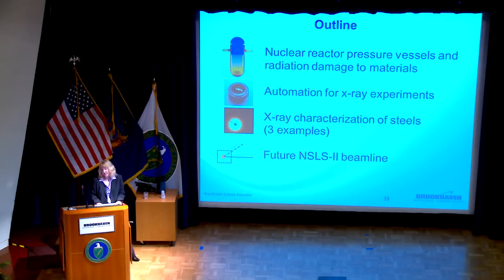What are the most common transmutation materials that are produced in these reactor vessels? We have neutrons, and presumably we're transmuting these steels into something which slowly changes with time, as you mentioned. I'm just curious as to what are these materials that are being created? There's a lot of, say, cobalt and some radioactive rare earths. So in the samples that we have, most of the radiation that's coming off is beta. And even though some of the samples have been quite high, when you wrap them in Kapton tape, it really reduces the amount of beta radiation coming off, and we're able to handle them at the light source.